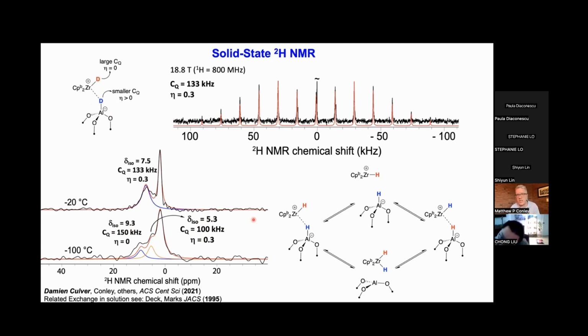We don't know the chemical exchange mechanism, right? One possibility is just fast reversible ionization. The other is that this ion pair breaks by the zirconium hydride falling onto a nearby Al-O-Al bridge and then recombines on the other side of the aluminum, or you could have a four-center transition state as well on the zirconium that could account for this.